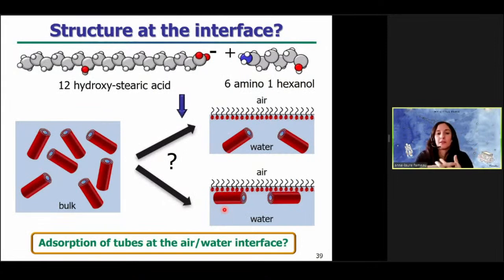Then we wanted to see what is the structure of these tubes at the interface, because we want to design some responsive aqueous foam. If you want to stabilize a foam, you need to have a foam stabilizer at the interface. So the main question was whether these tubes are just unfolded at the interface and form a simple fatty acid monolayer, or whether these tubes can go to the interface and adsorb below this fatty acid monolayer and act like solid particles, as in the case of Pickering foams.